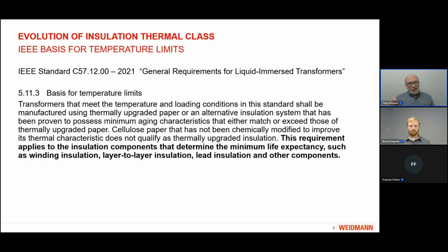And this has been defined in the standards as the winding insulation or the conductor insulation, or if it's a layer type winding, the layer-to-layer insulation or the lead insulation, anything that's in contact with the conductors. So what has been interpreted by this standard is that the pressboard, which is not adjacent to and contacting the conductor itself, does not need to be thermally upgraded.